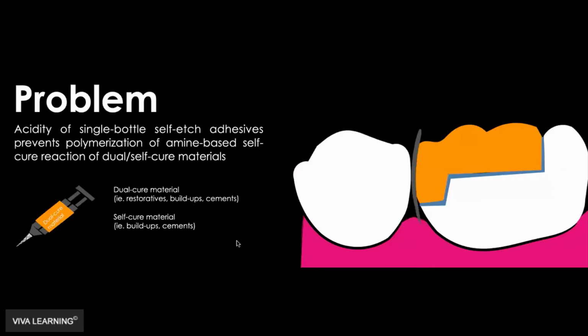All right, there's another issue though with dual cure bulk fill materials and adhesives. And it's not just Activa, it's many dual cure bulk fill materials. Actually, Activa doesn't have this problem, but many other dual cure bulk fill materials do. And that is that the chemical cure mechanism of dual cure buildup materials is inhibited by the acidity of single bottle self-adhesive bonding agents. In other words, in this cartoon, when you apply that blue bonding agent on the tooth, it's slightly acidic if it's a single bottle self-etch material, like many of our universal adhesives that are very popular in the market. They're all single bottle self-etch materials and they're acidic.